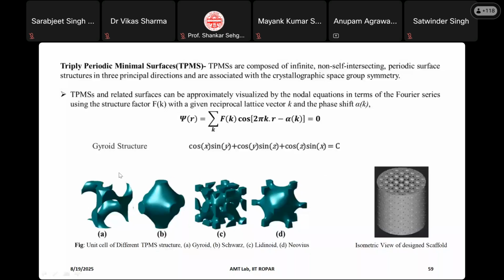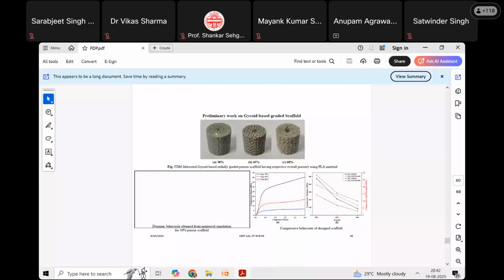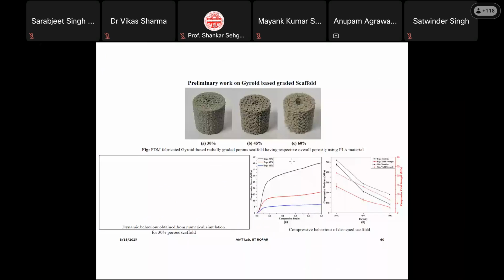One of those is the triply periodic minimal surface based structure. Not just by varying the material composition, but using the same material composition, we can vary the porosity and strength, going from outward solid to inward porous, using these mathematically defined structures. One of my students worked on developing a gyroid-based scaffold this way. He printed it using a polymer material, from outside solid to inside porous, using the triply periodic minimal surface, which is gyroid in this case.